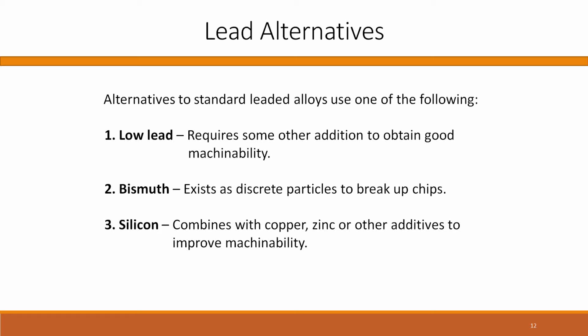For about 20 years, if it's a casting alloy or some of the rod alloys, the rod and cold drawn rods, they use bismuth. And bismuth doesn't mix with brass, just like lead doesn't mix with brass, so it's there as discrete particles. And silicon is now getting to be increasingly popular, something that they use that also does not mix with the brass matrix and is there as discrete particles.